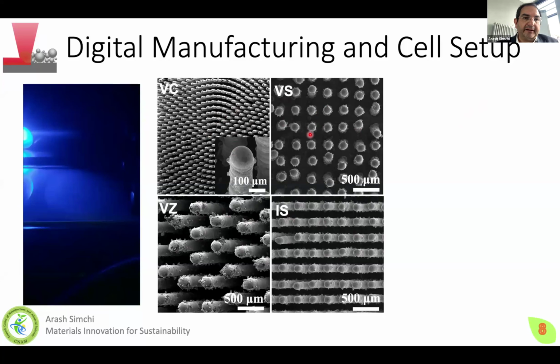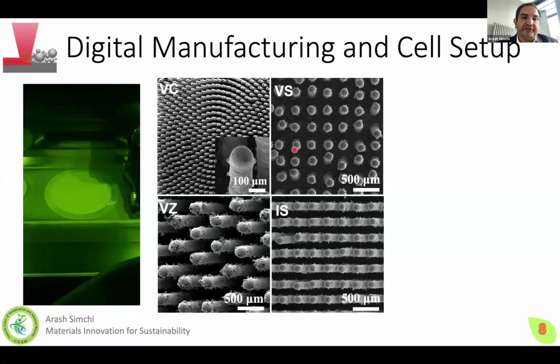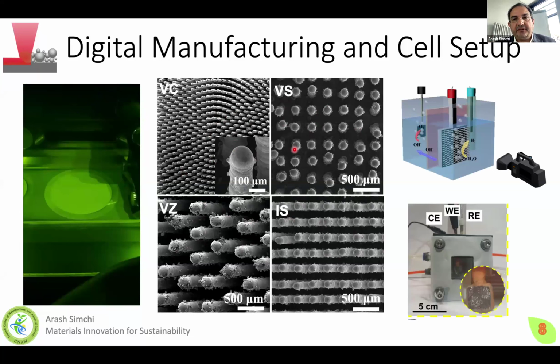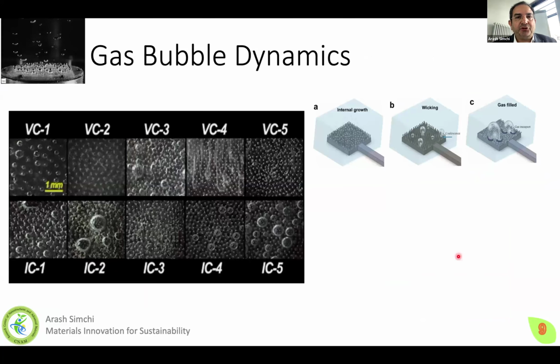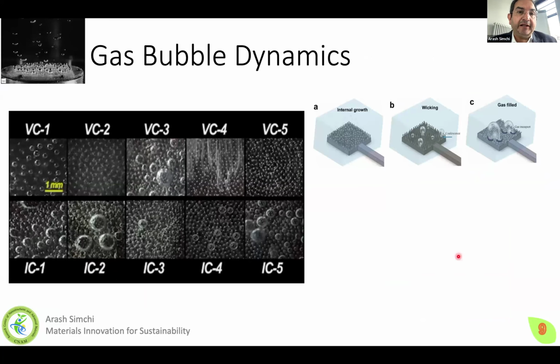And layer by layer, as you see in the film, a layer of powder is deposited and the laser is scanned on the surface. And then we design an electrolyzer in a way that, with a high-speed camera, we open a window inside an electrolyzer to see the bubble kinetics in situ, or in the operando condition. And you see our electrolyzer system. I would like to share with you some films.